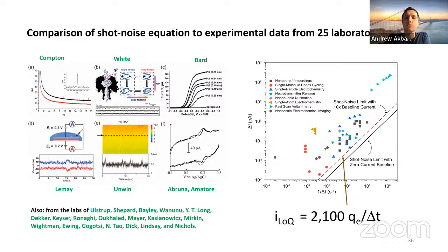It's quite helpful. We talk about this almost every day in my lab. Platinum nanoelectrodes: is your electrode stable? Has it recessed? Have you dissolved it? You can dissolve platinum in peroxide solutions or by going to too high of a potential, and sometimes it'll recess so you don't have a flat disk, and that's an issue.